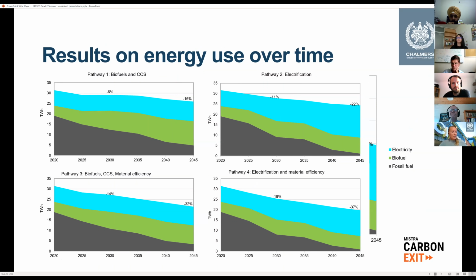And then what do we see as a result of this? Well, we see that currently construction of building and transport infrastructure in Sweden uses about 32 terawatt-hours of energy, which is about 8% of total Swedish energy use. And all the pathways demonstrate a reduction in total energy use over time, ranging from about 6 to 19% to 2030, and 16 to 37% to 2045. And when comparing the different pathways, we see lower energy use for the electrification pathways, mainly a result of lowered energy requirements for electric propulsion, and also looking at the energy penalty for post-combustion capture in cement plants.